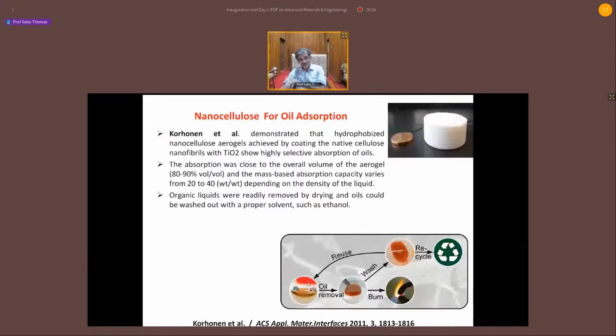Nanocellulose becomes resistant to water. You see? So all the oil is absorbed by the cellulose. Water cannot get in because it's hydrophobic. And then the oil is absorbed and you press it and you reuse the oil. Or you can burn it. So this is a way we can purify seawater. Korhonen et al. suggested that you make nanocellulose aerogel and sprinkle it in seawater, collect it after a while. And this way we can remove oil from water.